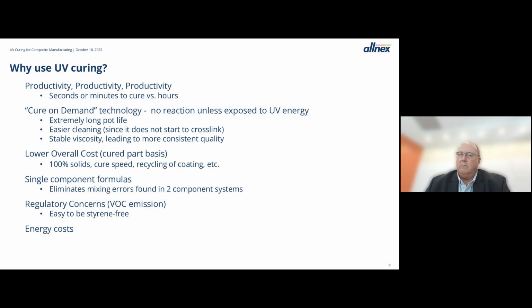And why is it used? Well, we mentioned earlier that it's a very, very fast process, and that's generally the driver for people looking at UV. It only takes seconds or minutes to cure with UV, and so your productivity, your throughput goes up accordingly. So it doesn't take hours to cure things, usually seconds, perhaps minutes if it's a particularly slow process, but even so, UV is generally a faster process to cure things than any other technology.